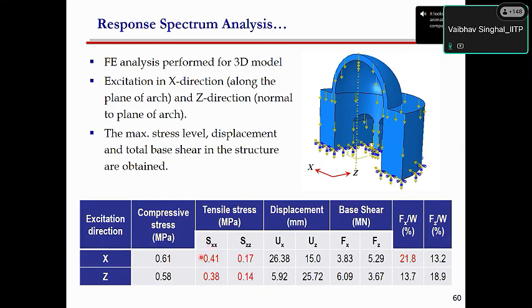So as you can see here, the tensile stresses are coming more than the capacity. If you remember from the test, we got a tensile strength of 0.11 MPa, whereas it has been found out from the response spectrum analysis that the tensile stresses at many locations exceed the limit capacity. So it is 0.41, 0.38. So this is close to the capacity. And also in one of the directions,